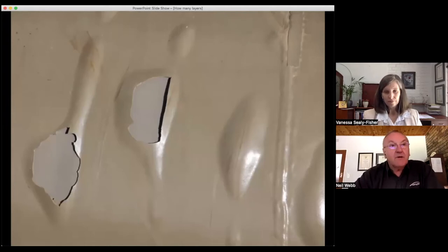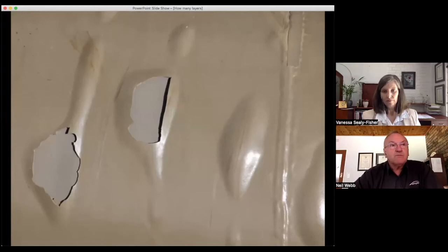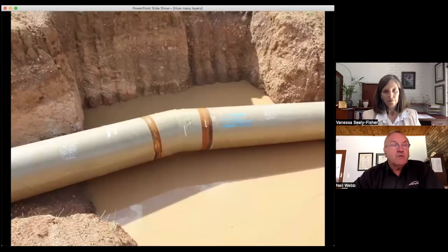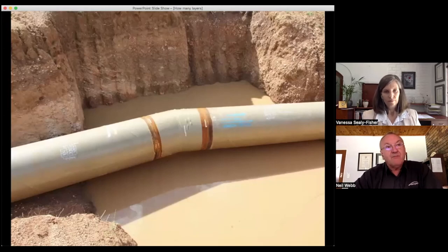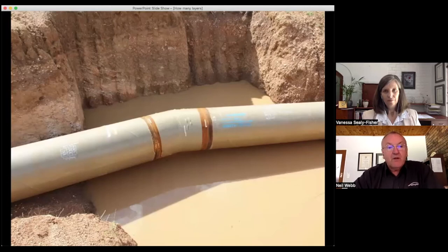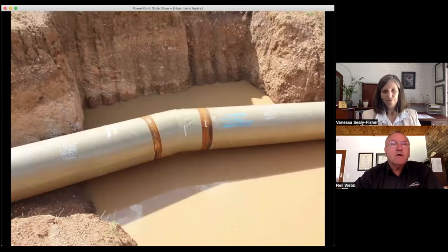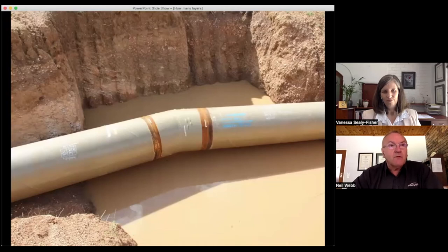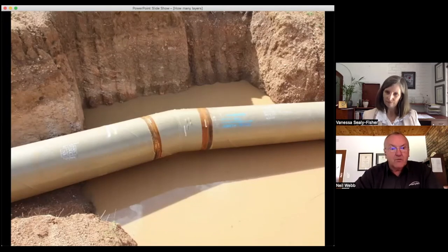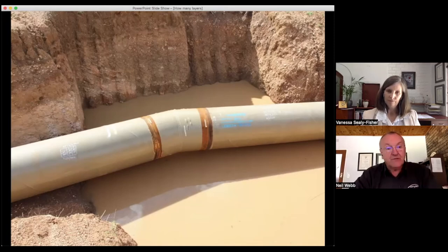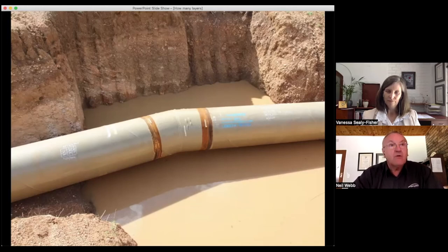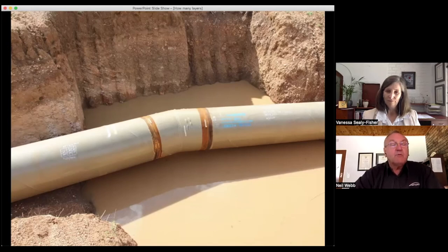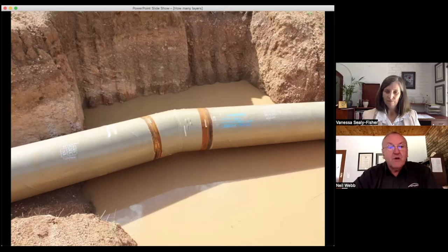What's interesting about this example is that this special had been manufactured in a factory under controlled environments and brought to site. Only about three months after installation did the blistering appear. It took time for moisture to diffuse through the coating and form that blister. So you've got a pipe that is apparently acceptable from all routine quality control points of view—hardness, cure, thickness, appearance, all normal non-destructive testing during application.